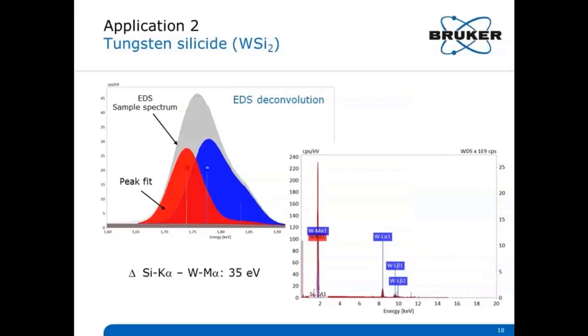Here's an EDS spectrum of tungsten silicide acquired at 20 kilovolts, showing the pathological peak overlap between silicon K lines and tungsten M lines. The close-up of the upper left shows the EDS peak deconvolution model, so fitting of the tungsten and silicon element peaks into the measured spectrum.